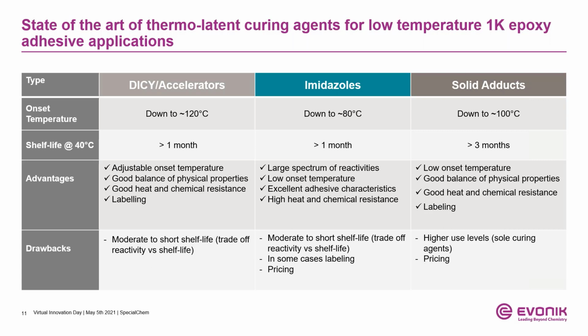The second technology involves imidazoles, which enable very low onset temperatures combined with excellent material properties, but also with the trade-off of reactivity and shelf life. Here, the higher price level and labeling issues in some cases are decisive drawbacks of this technology. The last technology, which combines low onset temperatures and high shelf life, as well as good material properties and also non-critical labeling, are the so-called solid adducts. Possible contradictions here could be the high price and in some cases the high use level of this technology.